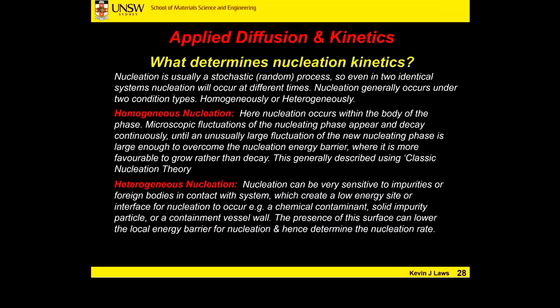Heterogeneous nucleation is by far the most common. For homogeneous nucleation, you have to have very, very clean conditions. Often the containing vessel is going to be the same as the material that you're nucleating, so that we don't provide any nucleation sites, or the vessel has to be a known poison to nucleation of that system. Most of the time in industry or in science, we're dealing with something that's not quite perfect conditions. Often our alloys will have impurities in them. We rely on them for strengthening and things like that. So they provide sites for nucleation, crystal growth, and solidification.